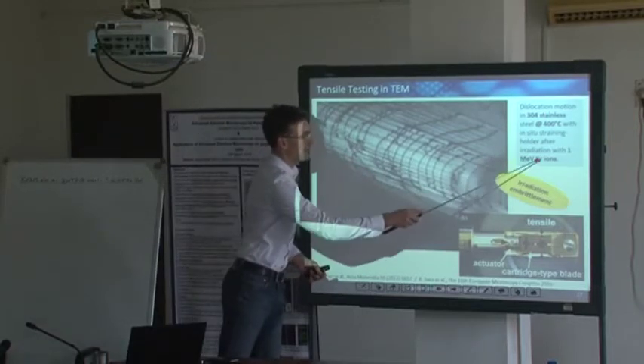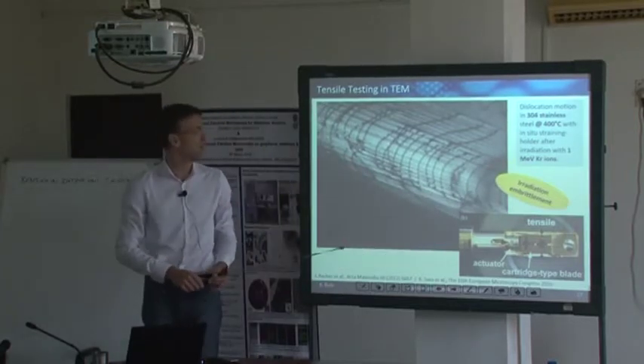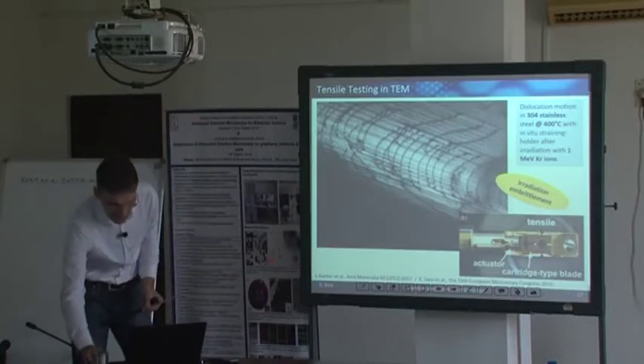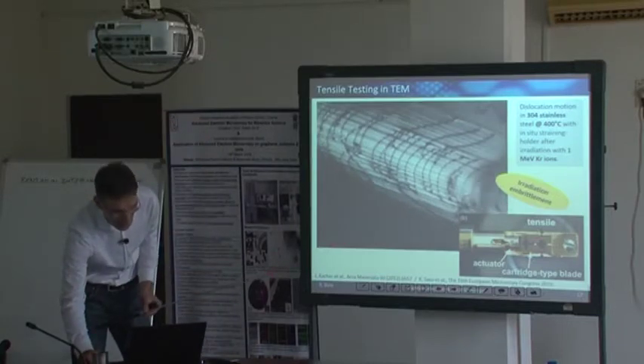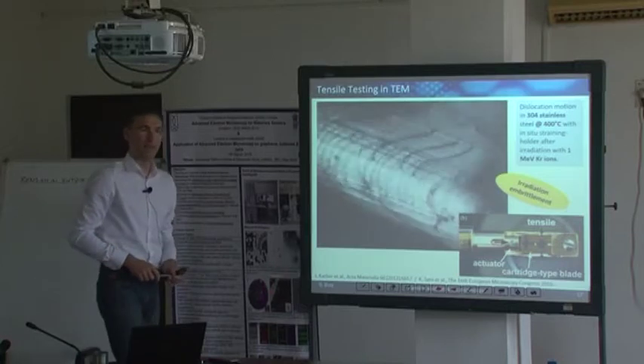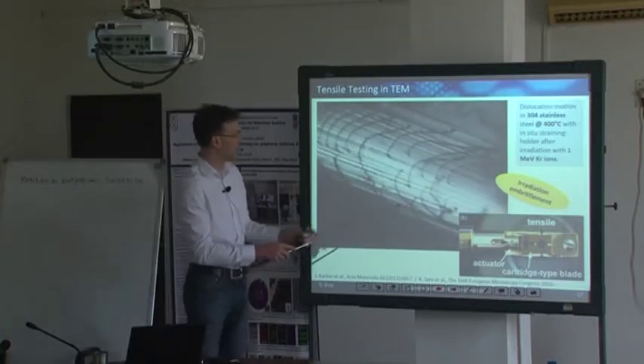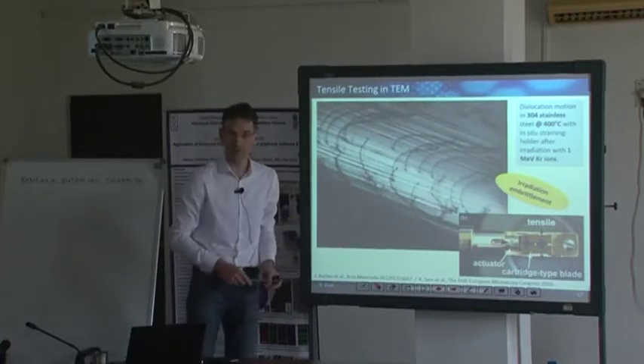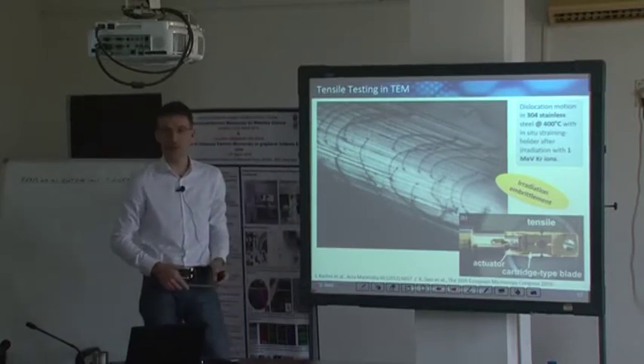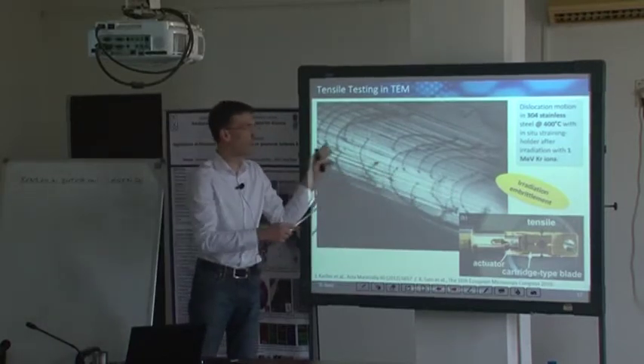This is a stainless steel that was irradiated, and that caused some hardening. So the movement of dislocations is strongly limited. And this is how you see that in bright field TEM imaging, where you can see all these individual dislocations moving through the material. And this is just the movement in one direction.